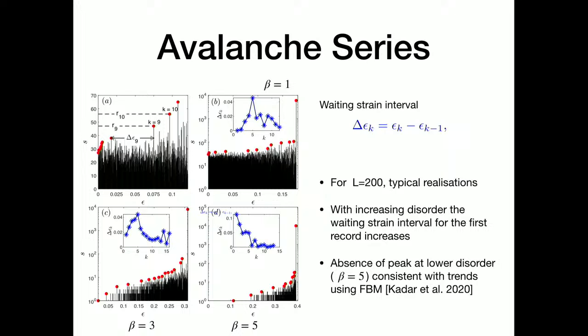If we look at the avalanche series of these, the first one here is just showing a typical one for system size 200 by 200. You can see that the black lines are the avalanches, and the red dots are the records. There are 1, 2, 3, 4, 5, 6. They're too close here, so not able to see that. But you can see that this is record number 9, record number 10, and that is the associated index k equal to 9, 10. And then there is this waiting, what we are calling the strain interval, because waiting time interval has been talked about. It is just a multiplicative factor because we are applying a constant loading rate.